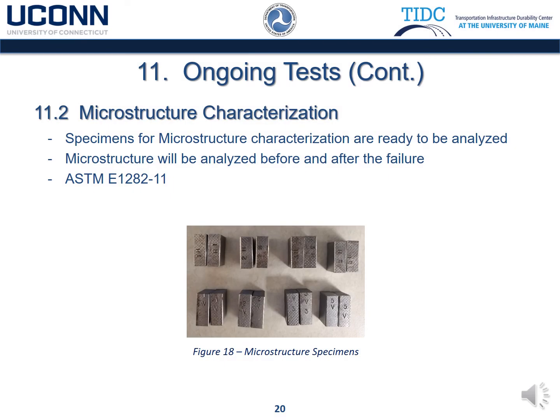Microstructure characterization. Specimens for microstructure characterization are ready to be analyzed. The test protocol will be defined by ASTM E1282, and the specimens will be analyzed before and after the failure.